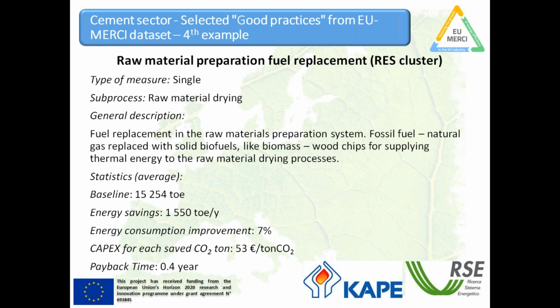The baseline of the measure is on average 15,254 TOE. The energy savings are large too. However, when we refer them to the baseline, they account only for 7% of the baseline. The capex for each ton of avoided CO2 emission is very low, and the payback time is very low because biomass can sometimes be considered a waste material, which is free, or which can be acquired at low cost. Also, biomass is often considered a zero emission fuel. That's why the capex per each CO2 emission saved is also low, because there was large saving in CO2 emission.